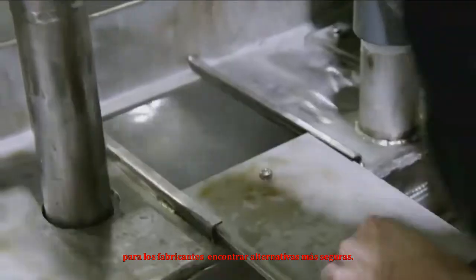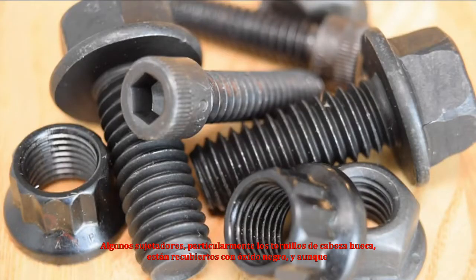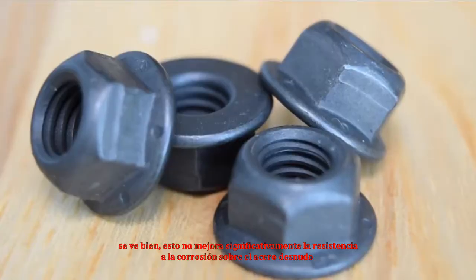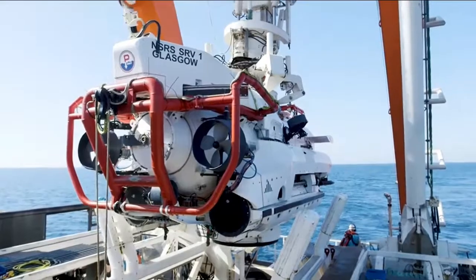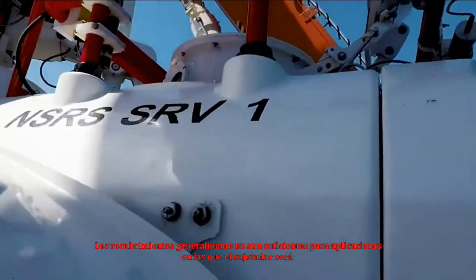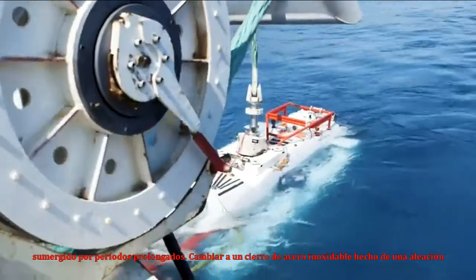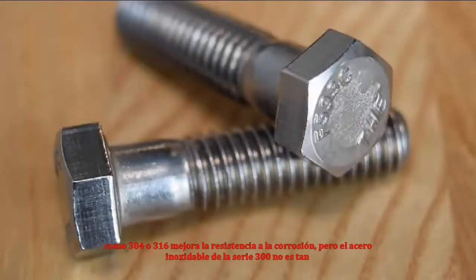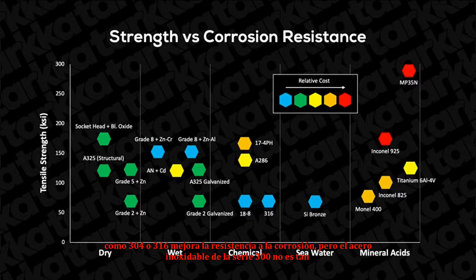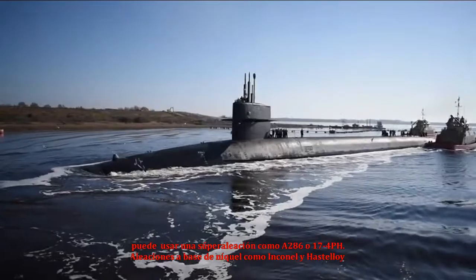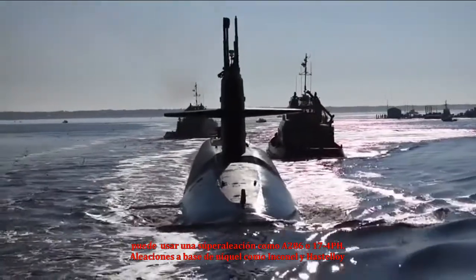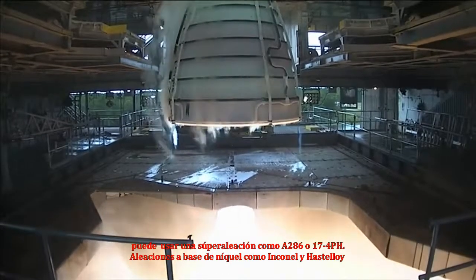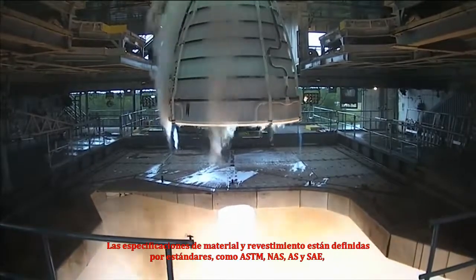Some fasteners, particularly socket-head cap screws, are coated with black oxide, and while it looks nice, this doesn't significantly improve the corrosion resistance over bare steel. Coatings are generally not sufficient for applications in which the fastener will be immersed for extended periods. Switching to a stainless steel fastener made from an alloy like 304 or 316 improves the corrosion resistance, but 300 series stainless is not nearly as strong as alloy steel. If you need both high strength and corrosion resistance, you may need to use a super alloy like A286 or 17-4 PH. Nickel-based alloys like Inconel and Hastelloy are also used in the most demanding applications.